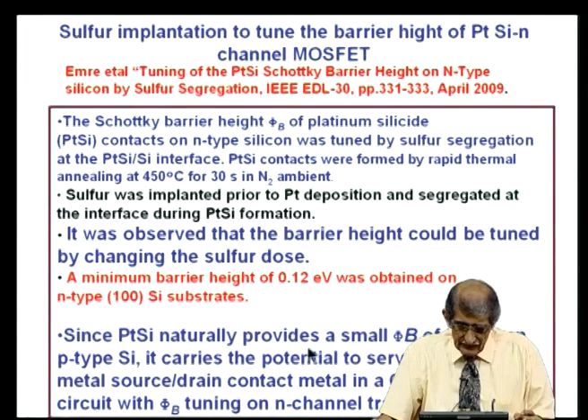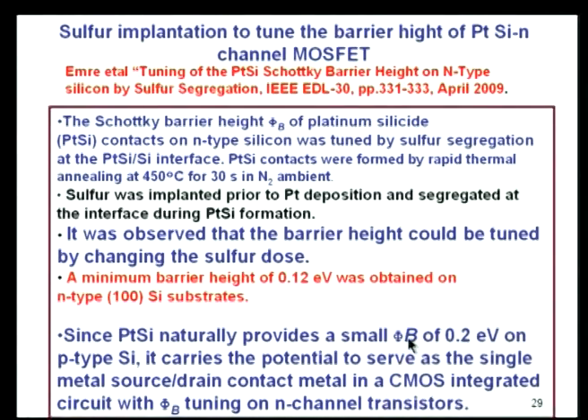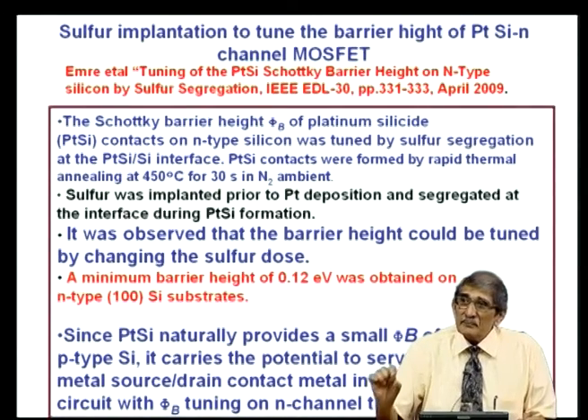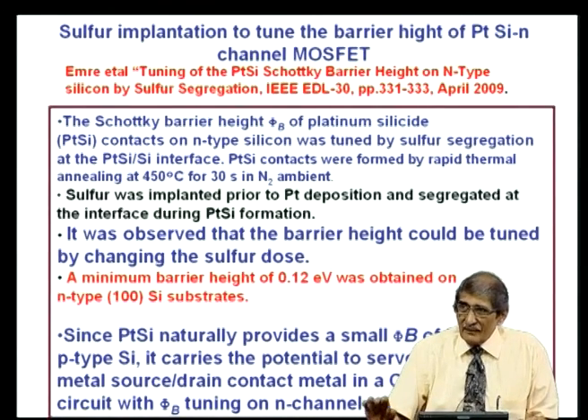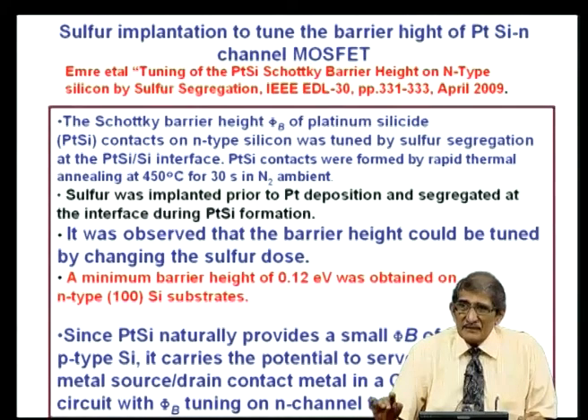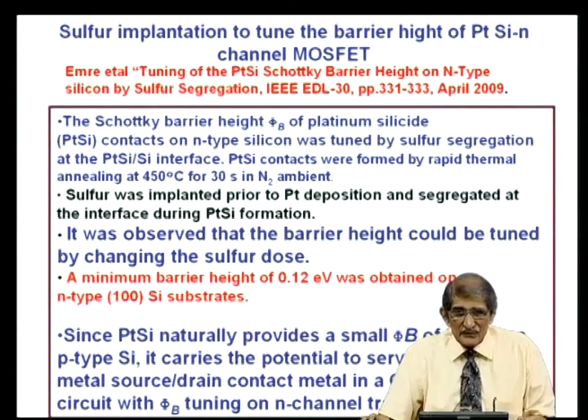Since platinum silicide naturally provides a small ΦBP, of 0.2 electron volts on p-type silicon, it carries the potential to serve as a single metal source drain contact metal on CMOS integrated circuits. I hope you understand that. Same platinum can be used. In the regions where you want to make p-channel MOSFET, do not implant sulfur. You get a barrier height which is ΦBP low for the p-channel, 0.2 electron volts.